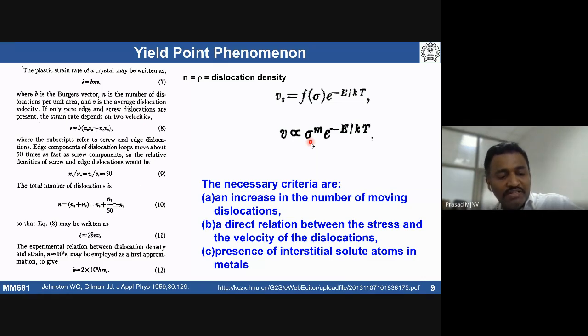How do you estimate how much carbon atoms, solute atoms, are required to pin the dislocations? Any idea? We are talking about a low carbon steel, which has some carbon content. How many carbon atoms are going to participate in pinning the dislocations? That's going to depend on dislocation density. Higher the dislocation density, one can expect higher the carbon atoms requirement for locking the dislocations. Can you say it like that?